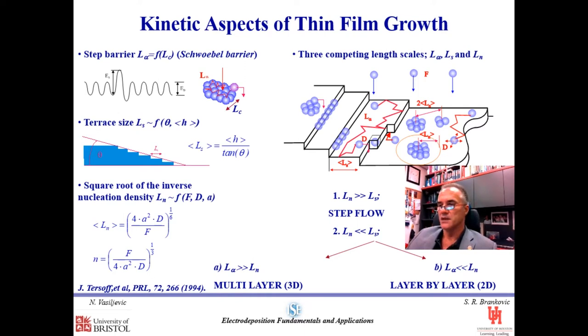The first length scale is L alpha here, which basically defines the strength of the Ehrlich-Schwoebel barrier, which is an extra barrier for an adatom diffusing on top of the cluster to step down and incorporate into the growing layer. The second one is L sub S, which is the length scale defined by the average width of the terraces, which is a function of the angle of the miscut with respect to the low-index plane of our surface and the average height of the step.